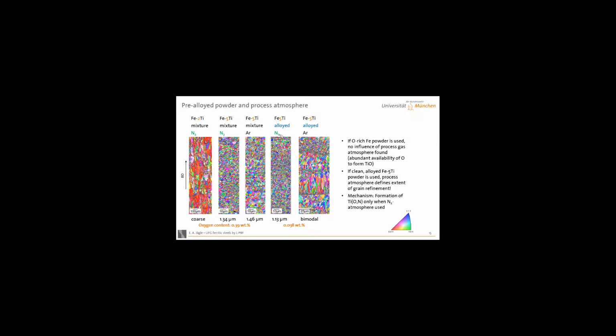So, given that it is much easier to just purchase some titanium nitride micro powder and throw it into the mixer, into the blender, you could question why we need this gas reaction at all. But I still think it's a neat idea on the one hand, and on the other hand, it of course makes your grain refinement switchable with one and the same material, or at least to some extent switchable. You could imagine processing parts of the material under nitrogen and other parts under argon, and then you could go from more or less elongated grains to equiaxed grains if you desire this change.